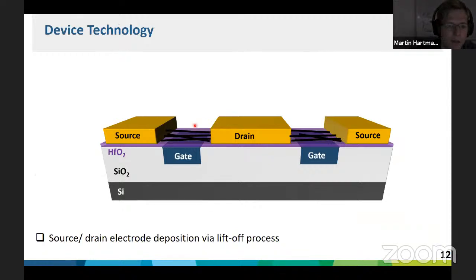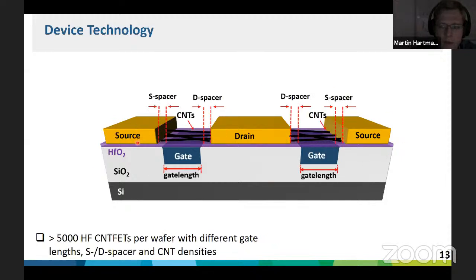Okay, so after depositing and structuring the CNTs, then via a lift-off process, we structure the source and drain electrodes. And this is almost it. So this is the device, how we operated it. And since we used two lithography steps, one for the gate electrode and one for the source and drain electrodes, we are fully free to design the geometry in any way we want. When you would use a self-aligned T-gate approach, then you don't have this freedom. But in our case, we can do this. We can define all the spacers to the extent we want.